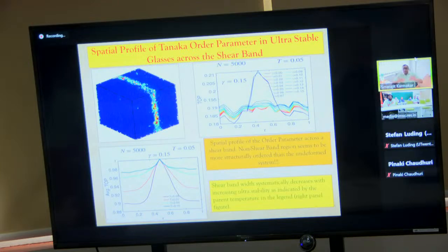So if you look at the shear band and cut through the profile itself, you see that the order parameter is very large in the shear band region. And interestingly, outside the shear band, the order parameter is much smaller than in your undeformed sample. If you compare the same structural order parameter in a non-banded region, it turns out to be smaller than in your undeformed sample, which tells us that somehow the non-banded regions became structurally much more stable, which is a surprise for us, and we don't have an answer to it. Hopefully in future we'll be able to get a good understanding by doing a better structural analysis of both the banded and the non-banded regions,